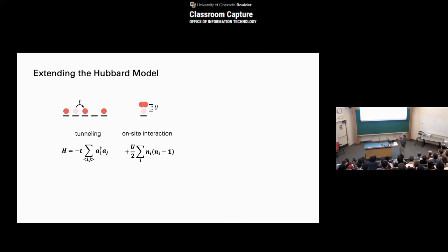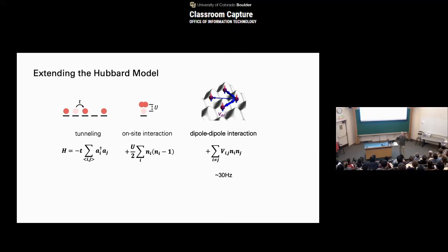Good. So now that we have this lattice, what can we do? We have the tunneling here. We have the on-site interaction. And now we also have a dipole-dipole interaction. So we get an additional term in the Hamiltonian: interaction energy, not just with two particles on the same site, but also if you have them on neighboring sites or even further away, they interact according to dipole interaction. And we can, of course, orient these dipoles and things like that. And as I said, this energy scale is about 30 hertz.